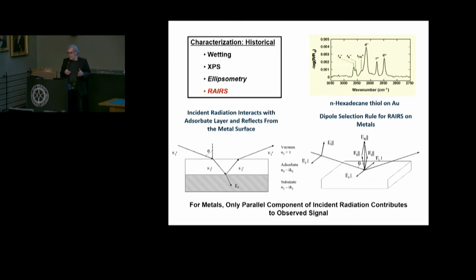We wanted structure. And one of the really important impacts came from doing infrared spectroscopy, and it's shown here in red, reflection absorption infrared spectroscopy. This is where I think one of the spectacular contributions that Dave made to this problem really came into play. Because early on, people thought this was a really interesting and possible kind of measurement, and one that had been discussed in the literature, but with the characteristics of instrumentation that was available at the time, would be essentially impossible to do.